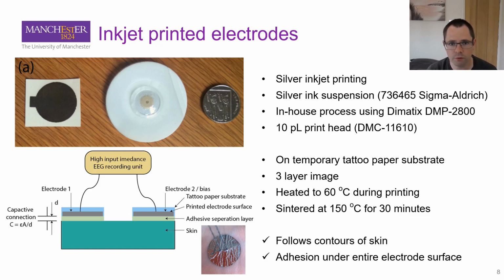So in panel A on the slide here, on the left there's one of our printed electrodes on a tattoo paper substrate, and then in the middle there's a conventional electrode. This one's actually for chest monitoring rather than the head, but it's the same principle. And the actual sensing area is just a small circle in the middle. All of the white circle around the outside is just adhesive. And so actually a lot of the total area of the electrode isn't being used for the sensing that we want to do. In contrast, our adhesive layer goes all the way under the electrode, and so the electrode is sized to the adhesion. And we're using all of the available space that we have to do sensing. And again, that should help decrease the noise floor, help us pick up very small signals.